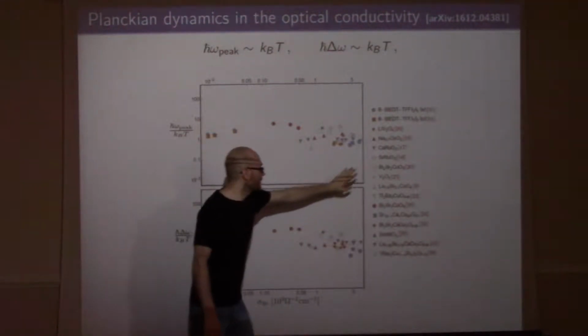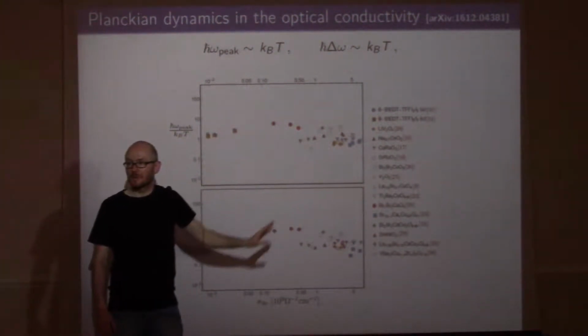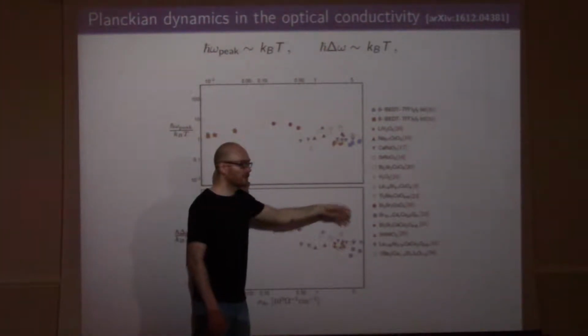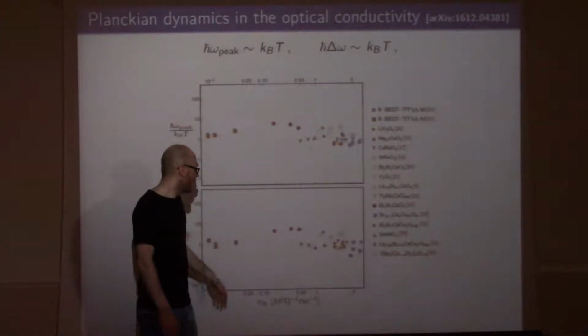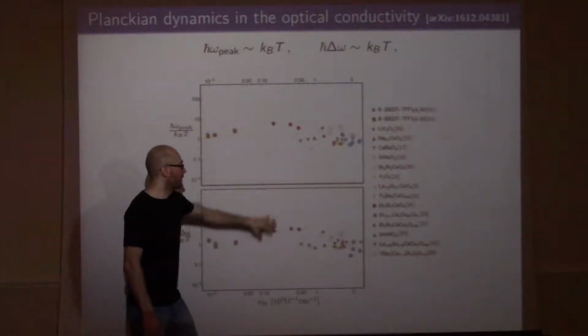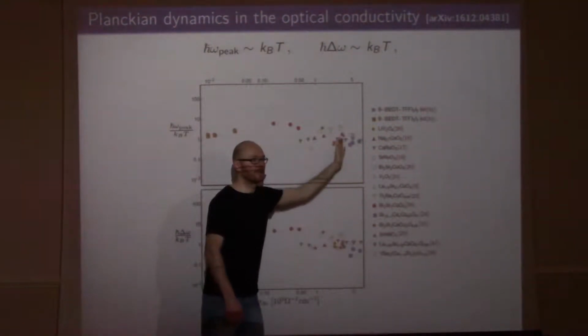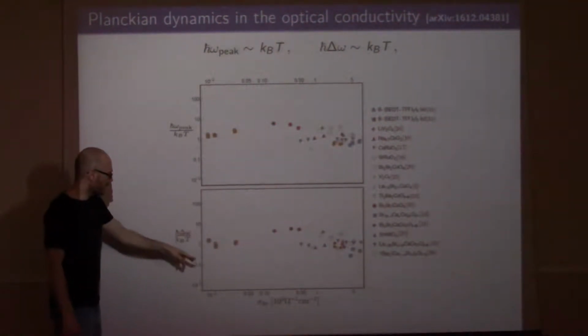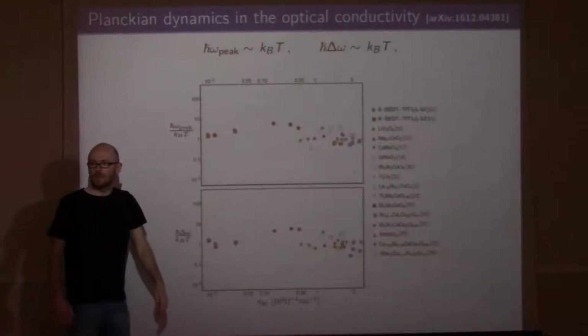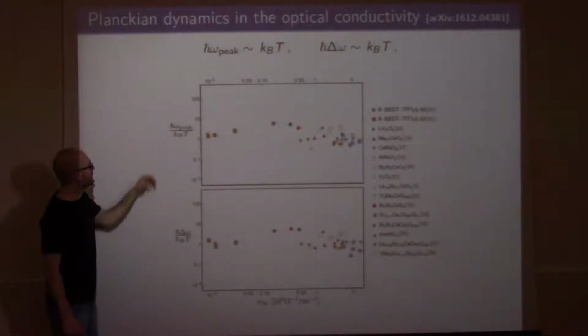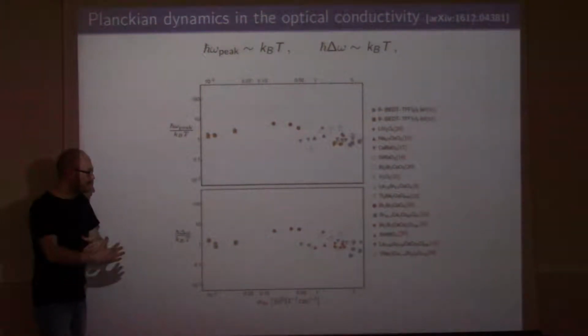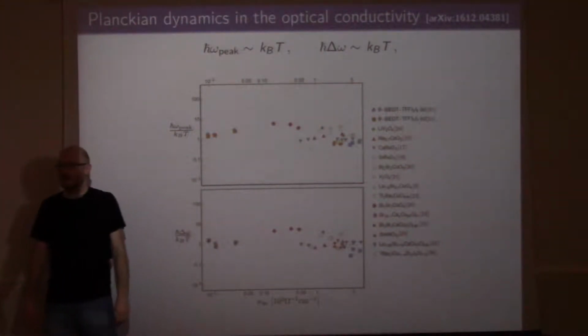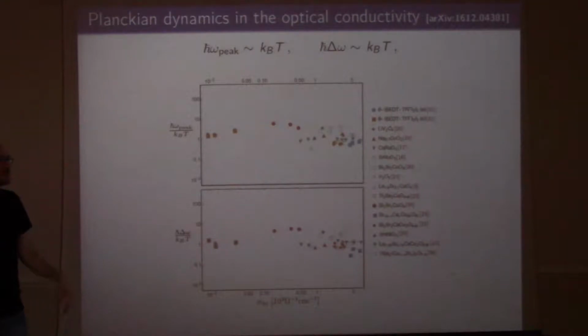All of these materials, you can look them up in the paper if you're interested, but let me not discuss them in any detail. There are high TC superconductors, but there are other types of bad metals as well. All of these materials are really bad metals because they all have DC conductivities that are below this Mott-Ioffe-Regel bound. This is a log-log plot, so you can see that there's some dispersion of the points, but still there's a general trend that the position of the peak and the width of the peak seem to be controlled by the same Planckian timescale as the DC transport. So the lesson here is that these Planckian dynamics show up not only in the zero frequency data in the resistivity, they also show up in the frequency-dependent conductivity.